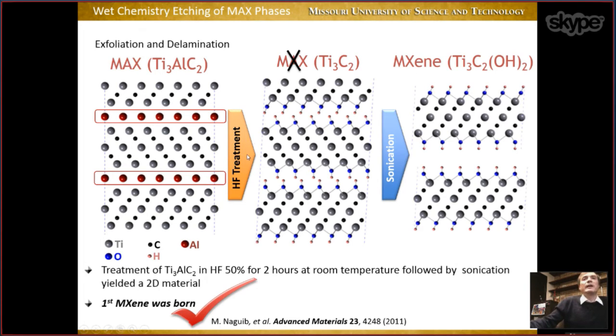Now, since we do this reaction in an aqueous environment, an aqueous solution of HF, the surface of the MXene layers is terminated by OH groups. So this is oxygen, hydrogen, oxygen, hydrogen. And then if we take this structure and sonicate it, we have separate layers of MXenes in solution. So this is how the first MXene was born. And again, this is Mike Naguib, first author of this paper, published in 2011. So that was the first MXene paper.